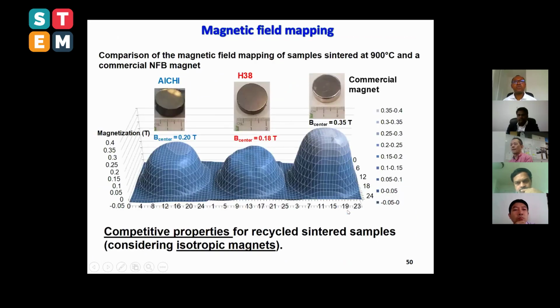And then you were able to record the magnetic field mapping in the bulk and compare with the commercially available magnet. This is the commercially available magnet, where you obtain 0.35 Tesla. And then we prepared two bulk magnets, with the commercial powder and with the recycling one. And we were able to obtain roughly, both are quite close, 0.2 Tesla with this material. But all this work is still ongoing. That means we should optimize our powder, find some parameters, and so on.